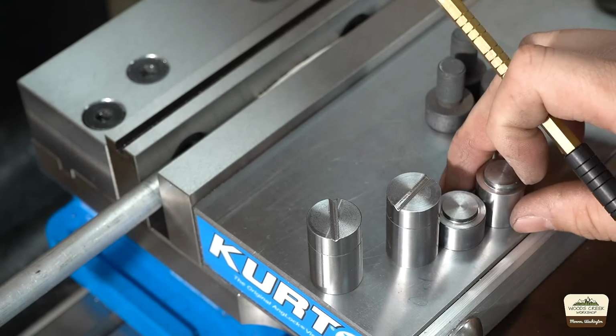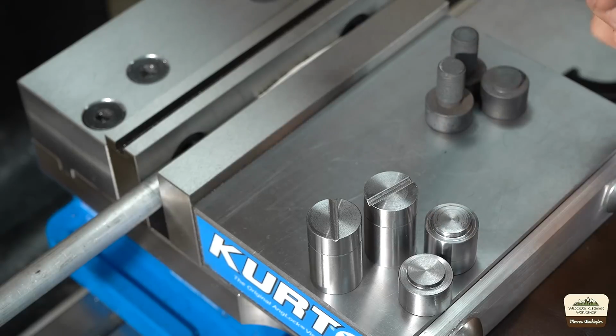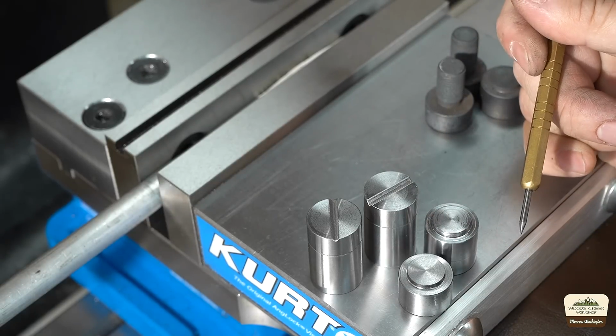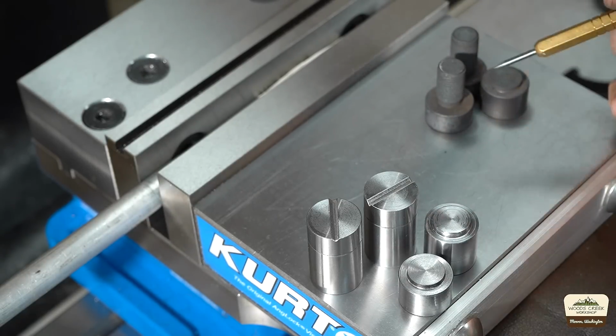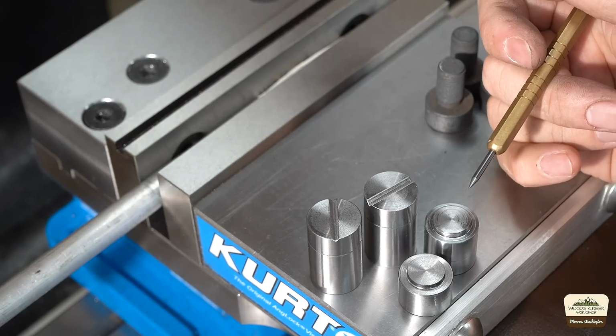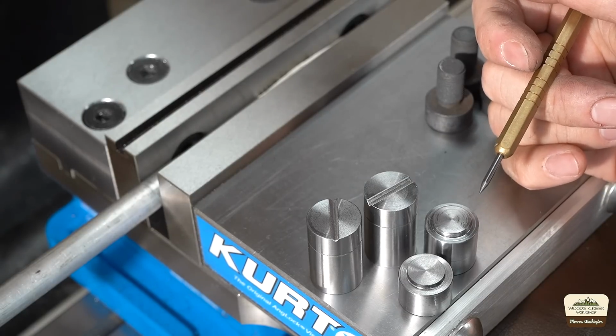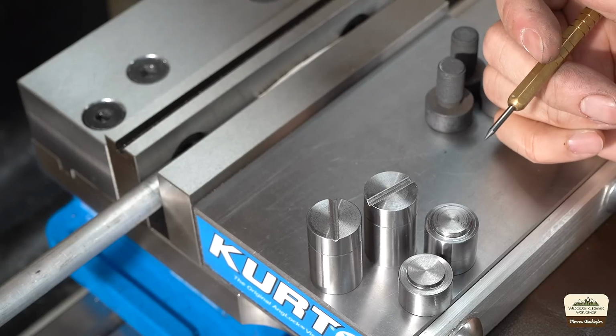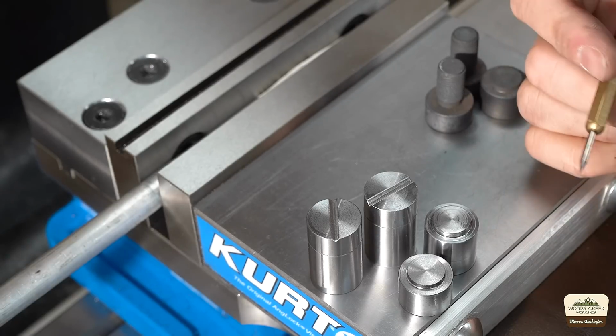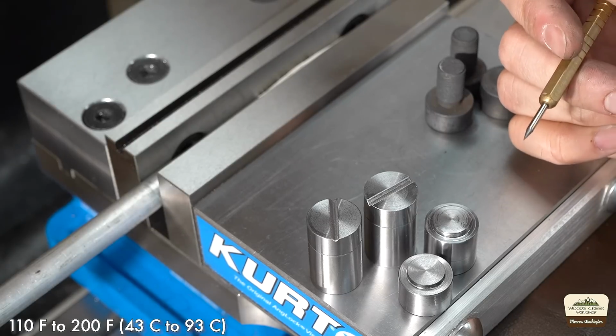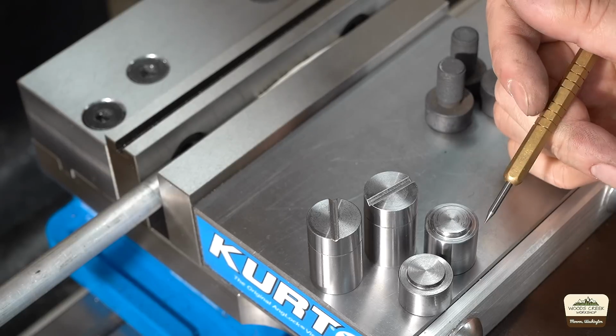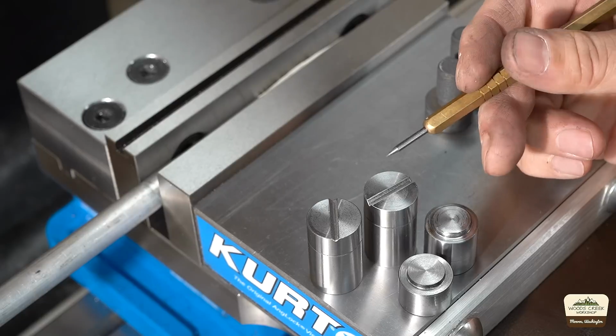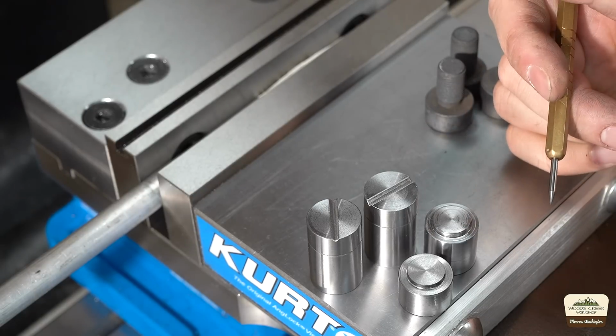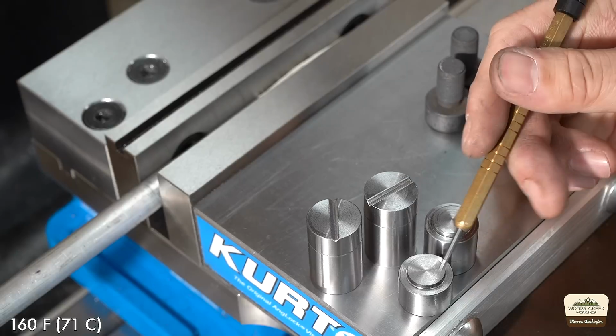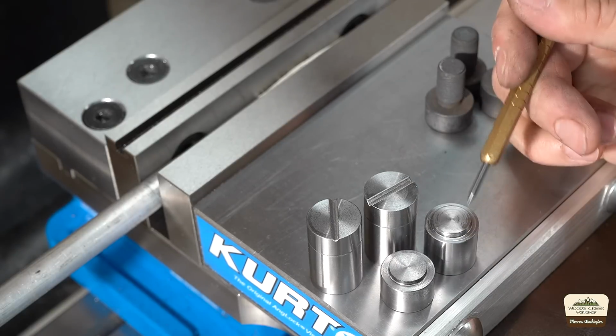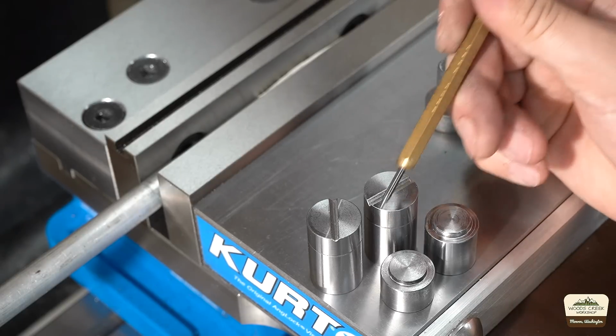And when it was time to quench these, I heated the water. I did a little more research between the parts, and they recommend that sometimes, depending on the application, you bring the temperature of the water up anywhere from about 110 degrees Fahrenheit to 200 degrees. I didn't measure it, but I boiled the water and let it cool off for a bit. So maybe 160, 170 degrees Fahrenheit. And I quenched in that, and that was just enough to ensure that these didn't crack.